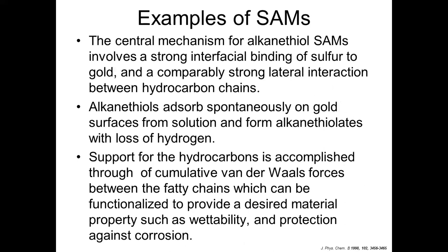It involves strong interfacial binding of sulfur to gold and comparably strong lateral interaction between hydrocarbon chains. Alkanethiols adsorb spontaneously on gold surfaces from the solution and form alkanethiolates with loss of hydrogen. The support for hydrocarbons is accomplished through cumulative van der Waals forces between the fatty chains, which can be functionalized to provide a desired material property such as wettability and protection against corrosion. Or we can cross-link those fatty acid tails with other biomolecules for some functionalized drug.